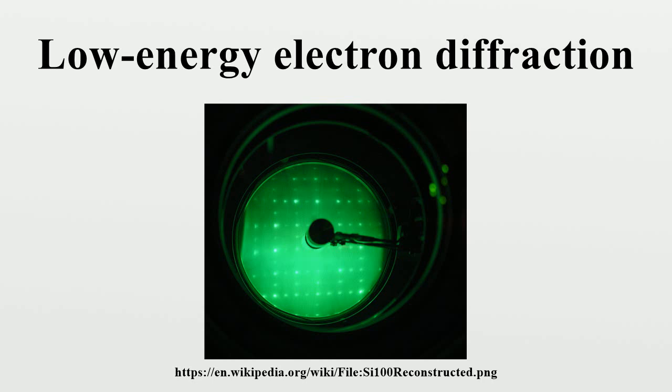Though discovered in 1927, low-energy electron diffraction did not become a popular tool for surface analysis until the early 1960s. The main reasons were that monitoring directions and intensities of diffracted beams was a difficult experimental process due to inadequate vacuum techniques and slow detection methods such as a Faraday cup. Also, since LEED is a surface-sensitive method, it required well-ordered surface structures. Techniques for the preparation of clean metal surfaces first became available much later.